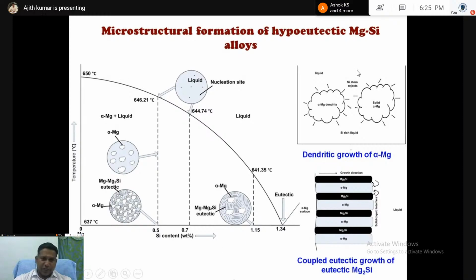That we can discuss using this phase diagram. This is a partial phase diagram from 0 to 1.34. 1.34 is the eutectic point of the magnesium silicon system. So if you solidify from the liquid melt, the melt temperature is 720 degrees centigrade, then continuously we are reducing its temperature or switching off the furnace.